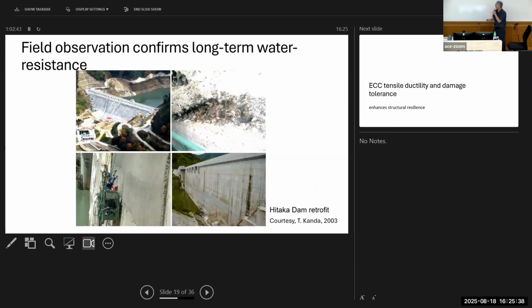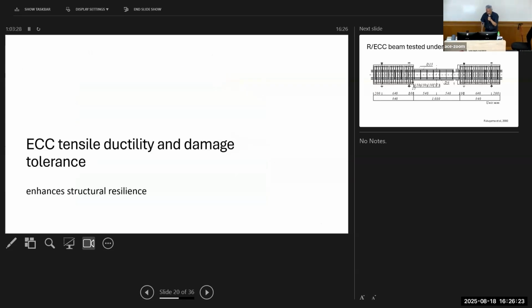Okay, so here is another application, also in Japan, in a reservoir, and this dam, called the Hitaka Dam, was retrofitted with ECC on the upstream surface, using a sprayed method. The reason behind this repair or retrofitting was the observation of erosion of the concrete, and they were worried that water gets through faster and faster through the dam, eventually causing damage to the villages below it. So this works out very well. So far, it has held up, a case of durability confirmation in the field.